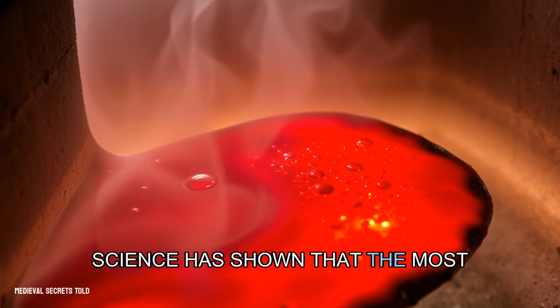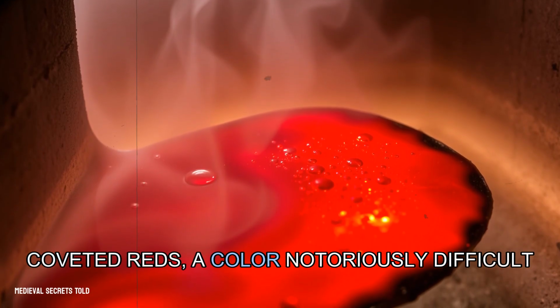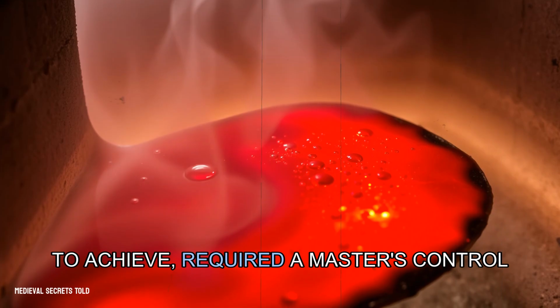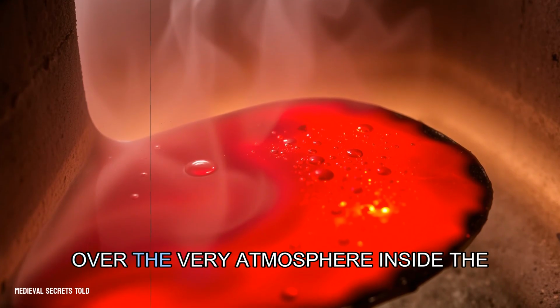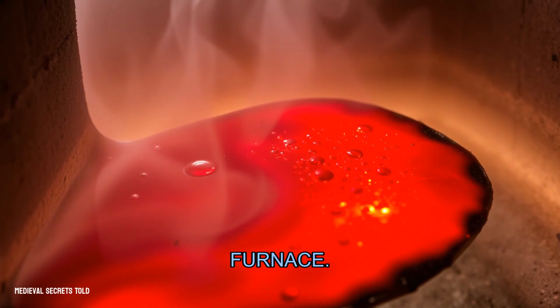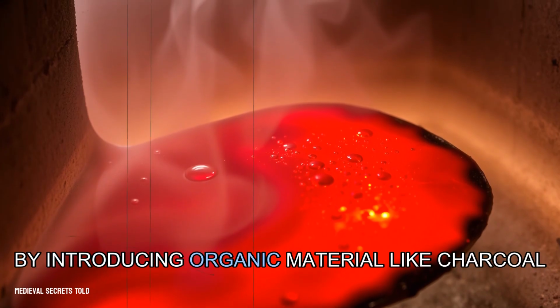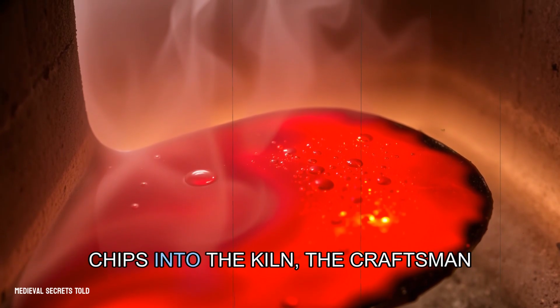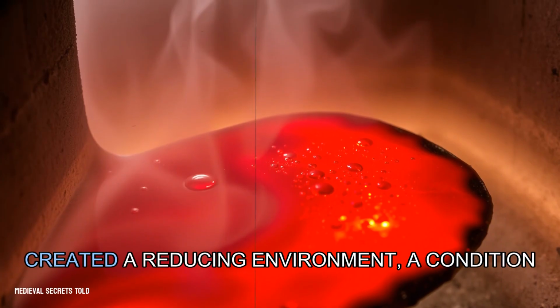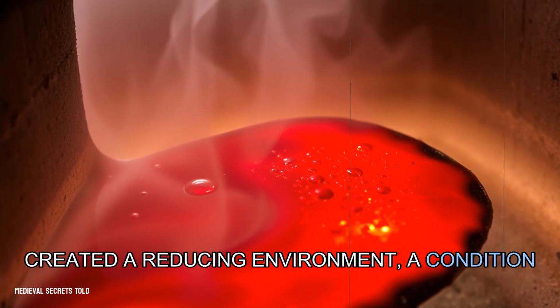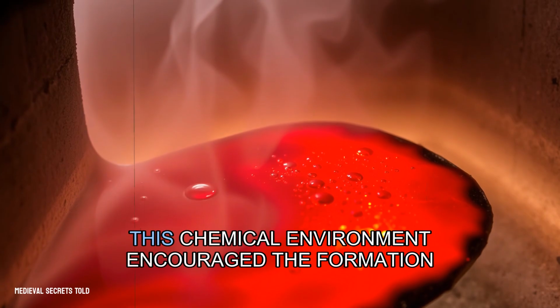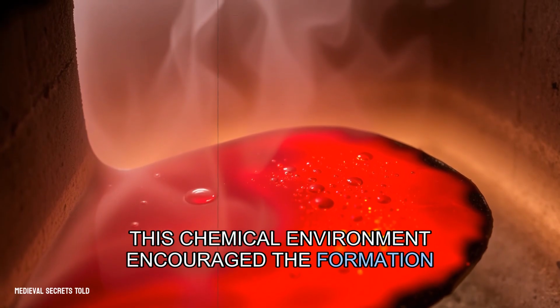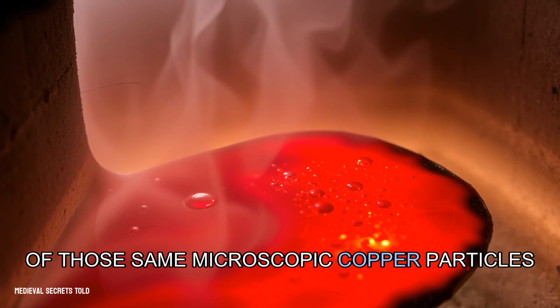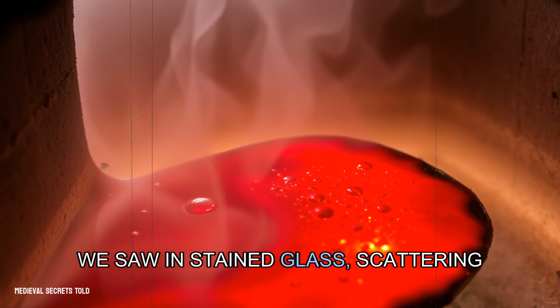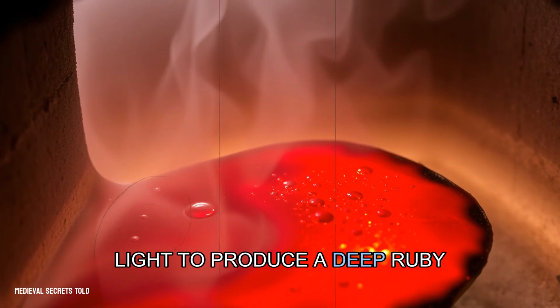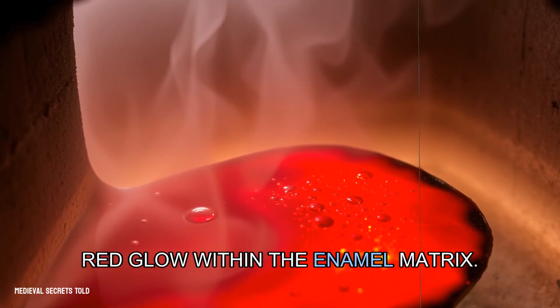Science has shown that the most coveted reds, a color notoriously difficult to achieve, required a master's control over the very atmosphere inside the furnace. By introducing organic material like charcoal chips into the kiln, the craftsman created a reducing environment, a condition low in oxygen. This chemical environment encouraged the formation of those same microscopic copper particles we saw in stained glass, scattering light to produce a deep, ruby-red glow within the enamel matrix.